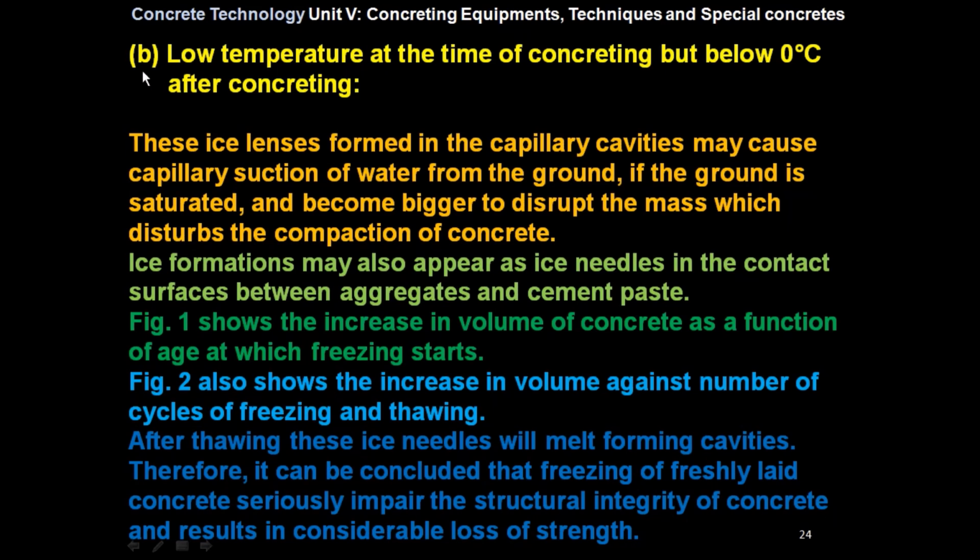Second, low temperature at the time of concreting but below 0 degree Celsius after concreting. These ice lenses formed in the capillary cavities may cause capillary suction of water from the ground if the ground is saturated and become bigger to disrupt the mass, which disturbs the compaction of concrete. Ice formations may also appear as ice needles in the contact surface between the aggregate and cement paste.